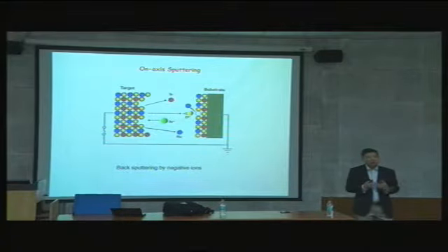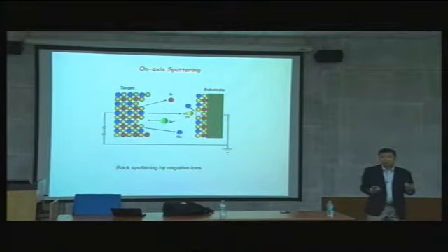Most sputter deposition, what you guys use, has only a few variables. Very simple variables. One, the partial pressure of the gas in it. Two, the power you apply, which includes the voltage and the actual current on the target, which is automatically adjusted. And then the temperature of your deposition. Very simple, that's it. Not much flexibility in what you can control.